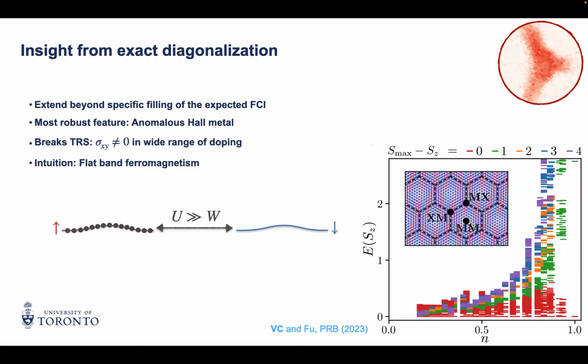Right. And in all of this part of the phase diagram, there's a spontaneous breaking of time reversal symmetry just because you polarize all of the electrons into one of the spin components. The intuition for why is you get a flat band. If you really have an exact flat band and fully fill it, it's better to fully fill one of the spin components only if you have local interaction, because of the Pauli exclusion principle that prevents you, like you win. You don't pay any kinetic energy if you have a flat band, and you also don't pay any interaction energy if interactions are local. Are you talking now about explanation of experiment or prediction?